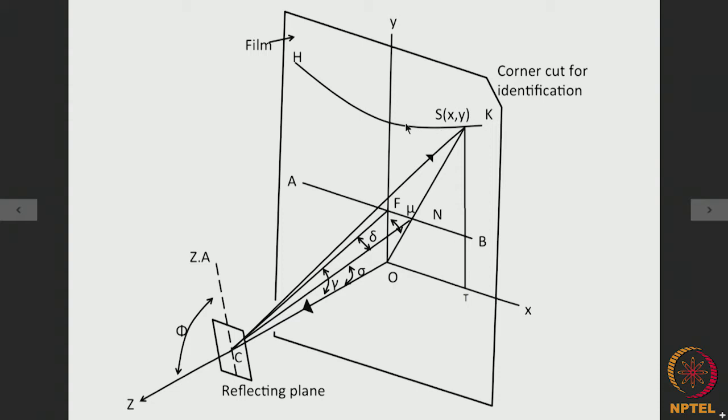So, all the diffraction spots from a number of planes forming a zone will appear on this hyperbola. And what happens to the plane normals for all the planes belonging to that particular zone? Their locus will be on this straight line which is perpendicular to the OY axis.